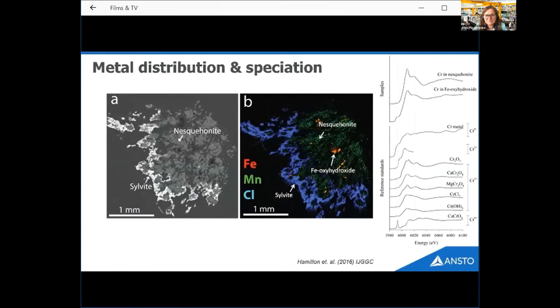So in the carbonate mineral, which is nesquehonite, we can see manganese is distributed really evenly, in green, through the carbonate mineral. But there's also manganese in the iron oxide, little spots in orange there too. We looked at a whole range of different transition metals, and we're also able to investigate the oxidation state for chromium too, to see if we are likely to generate toxic chromium in this system. So on the right, we're looking at the absorption spectrum for chromium. So on the bottom, we kind of list our reference compounds.